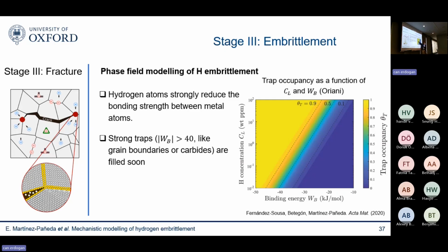So we are somewhere here. And here you can see a plot of Oriani's equilibrium, where you see trap occupancy. Yellow means fully occupied, blue means empty. This is the lattice hydrogen concentration, and this is the binding energy. So for grain boundaries, we're somewhere here. And you can see that for typical hydrogen concentrations like 1 ppm, your grain boundary is essentially full. Even at 0.1 ppm, your grain boundary is almost full. So it is energetically favorable for the hydrogen to sit in those grain boundaries, to accumulate in those defects.